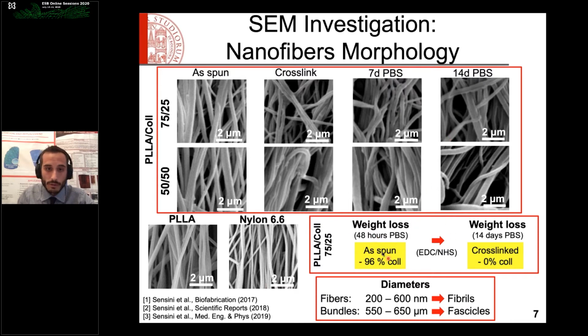As you can see from these gravimetric results on our bundles, in this case the 75-25 blend, before cross-linking, just after 48 hours in PBS, the bundles lost 96% of their collagen. But after the cross-linking process, the bundles and nanofibers were able to maintain the collagen inside them even after 14 days in physiological environment, losing practically 0% of collagen.